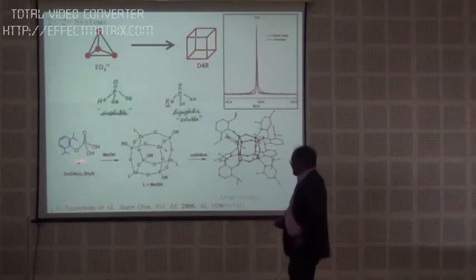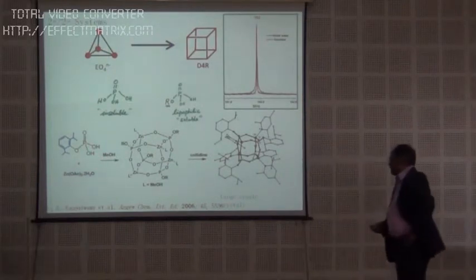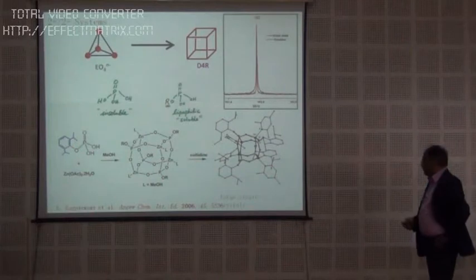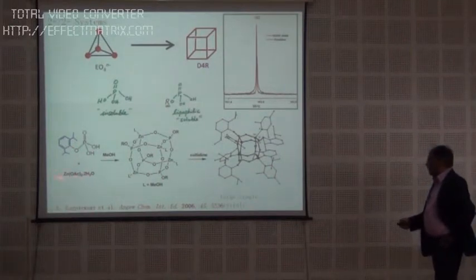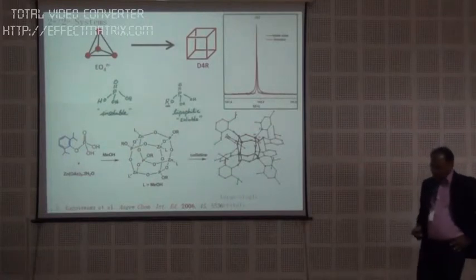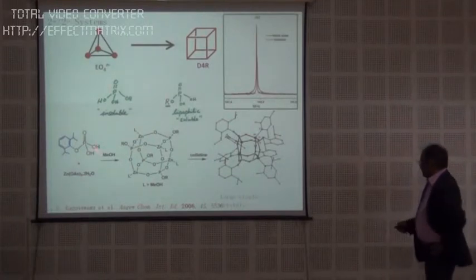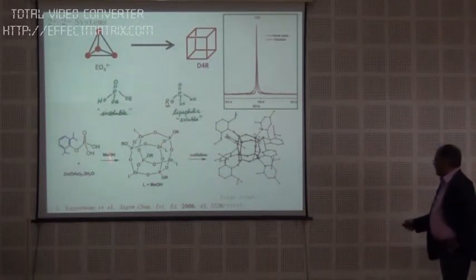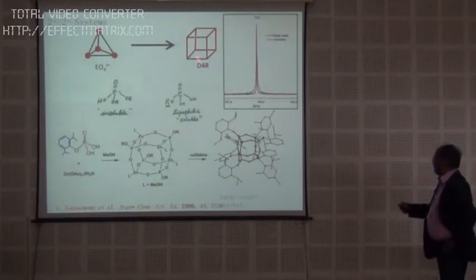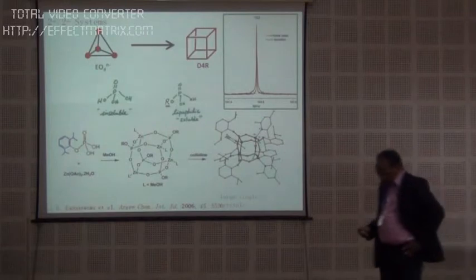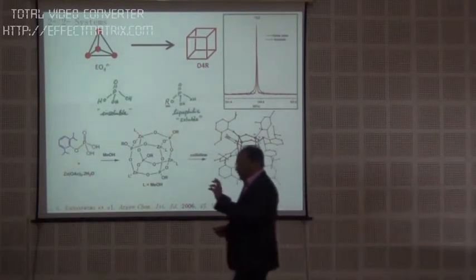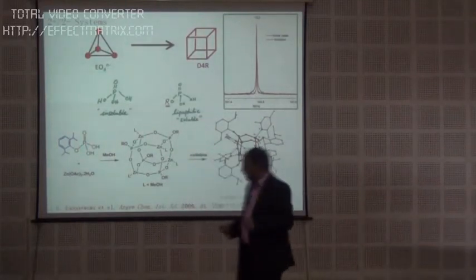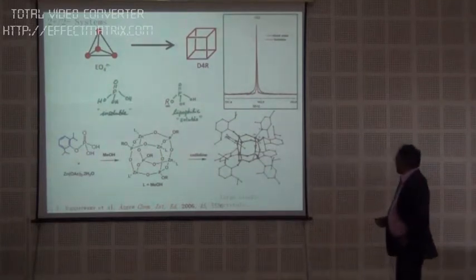Initially we were working with metal alkyls like dimethyl zinc, dimethyl cadmium, and so on. And soon we realized that you don't even need organometallic reagents. You can do it with acetates. We were using dry THF and dry hexane for the reaction, then we realized even dry methanol is good enough, and we did prepare the double 4 ring, which was shown to be one of the nice building blocks. Then we crystallized this and convinced ourselves and others that we do have a cutout of a zeolitic material as a soluble molecule which can be used for other purposes.